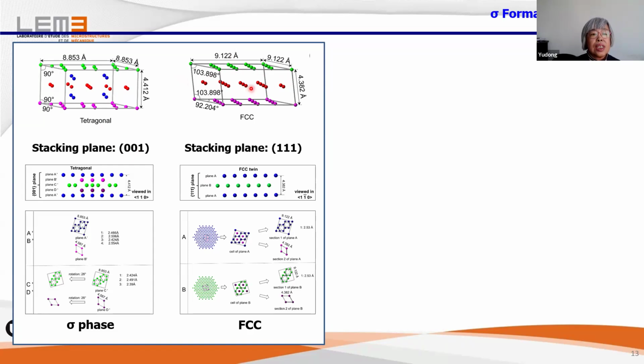And now we are interested in the atomic configuration, how the atoms are arranged in each phase. Then we put the FCC 111 plane here, you see, like this. And if we outline a unit cell, it looks like this. And if we put the sigma A prime plane here and B prime plane here with different colors, these different colors only resolve the layer, but not atomic species. And then we put them here. You see, for the blue one is this configuration, and for this is this configuration. If we put them together, it is exactly this 111 plane. And then the question is how these 111 planes moved these atoms to make such a motif.